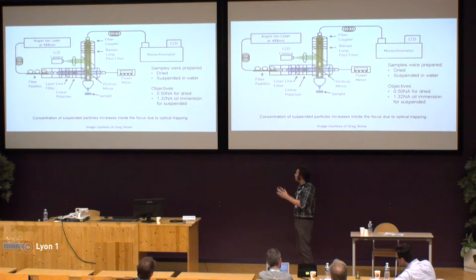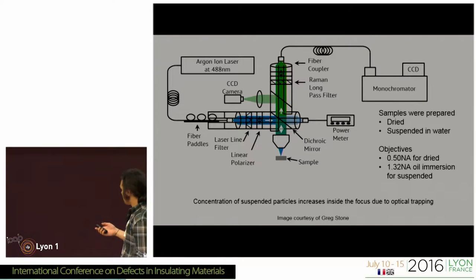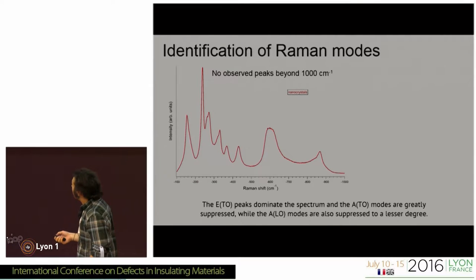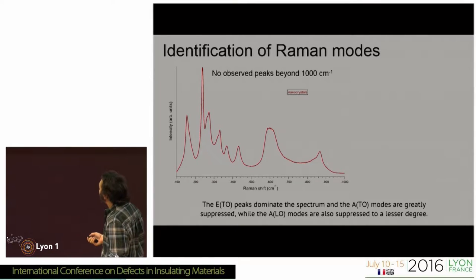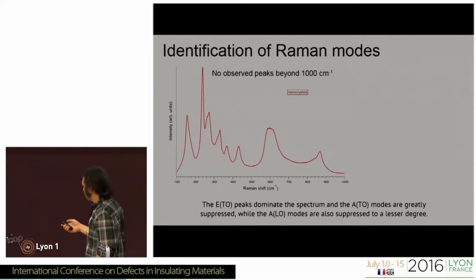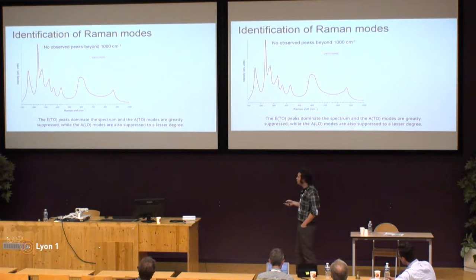We made a bunch of different batches of different compositions, and I did Raman spectroscopy. In that case, you have kind of an optical trap where the nanocrystals densify around the focus, and then you can collect the spectra. Here's a typical Raman spectra for the nanocrystals, and I did peak fitting to do a sort of mode assignment using the most recent mode assignments in the literature.